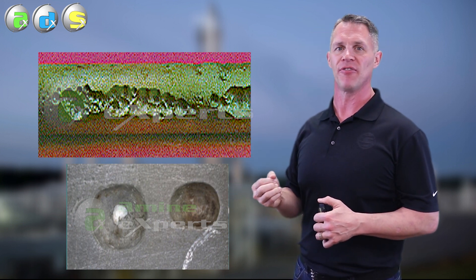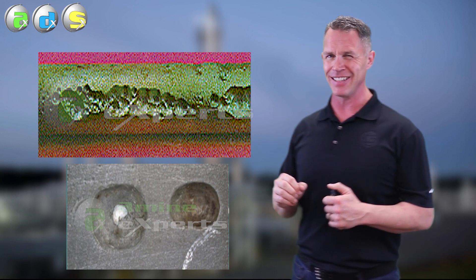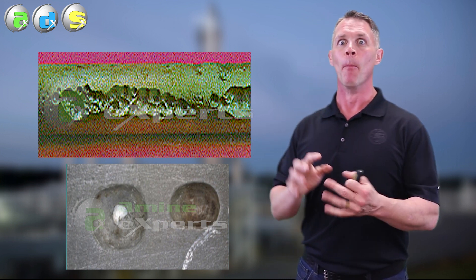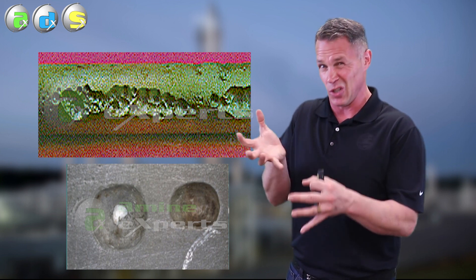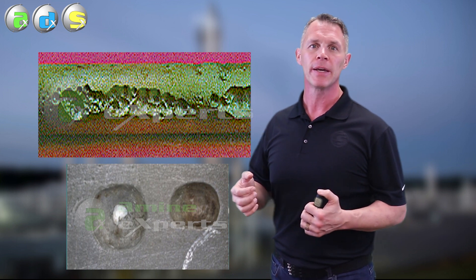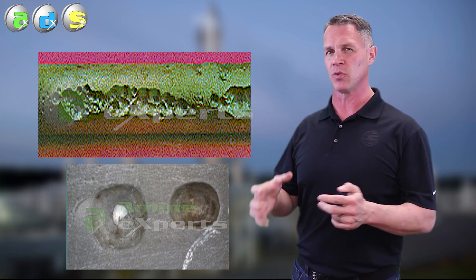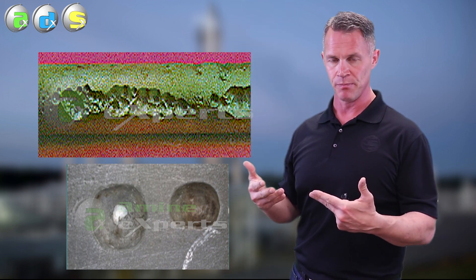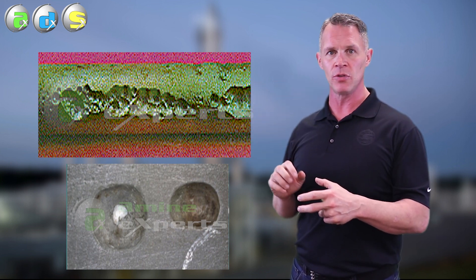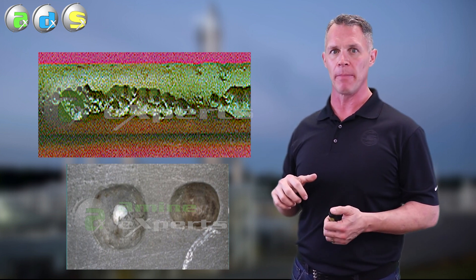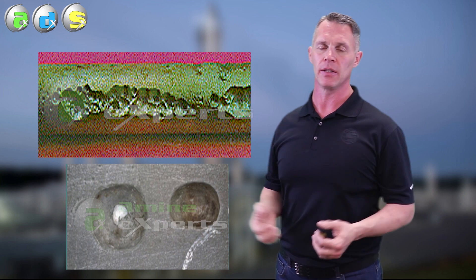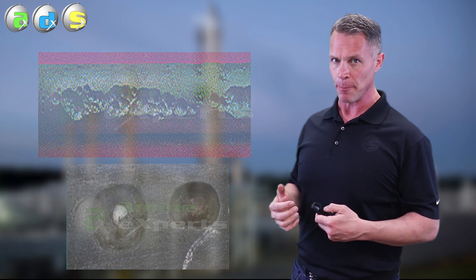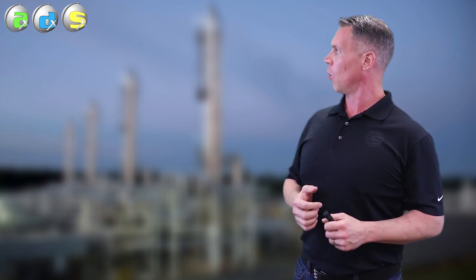CO2 plants do form a film on the metal wall, similar to an iron sulfide film, but in a CO2 plant it's iron carbonate. The difference is that iron carbonate is far less protective — it's more soluble, especially if the amine has some heat stable salts in it, which will just dissolve the film. Also, in high-velocity or turbulent areas you get a porous film, meaning CO2 molecules can get in behind it and attack the metal wall.